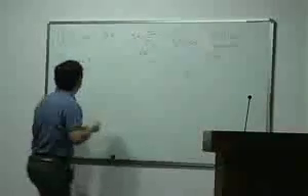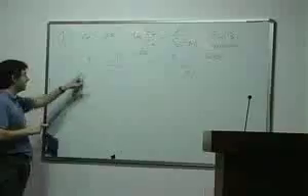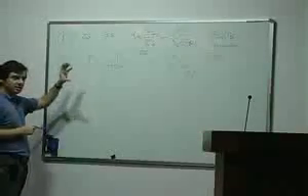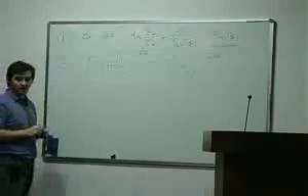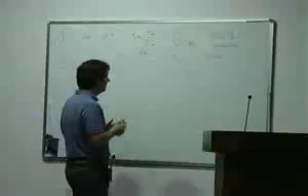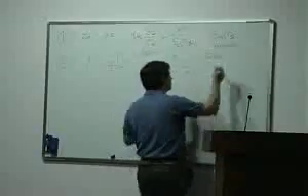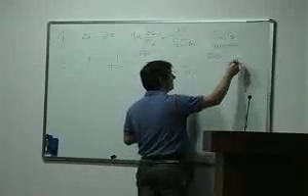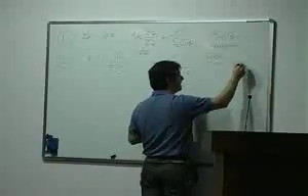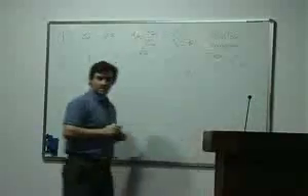Again, this is universal at Tg, so glass formers all have the same length: the length of the mosaic is the same for all glass formers at Tg. I'm not doing the computation, but if you put in all the values, Wolynes says that this is something like 6 times a, where a is the microscopic length. Okay?